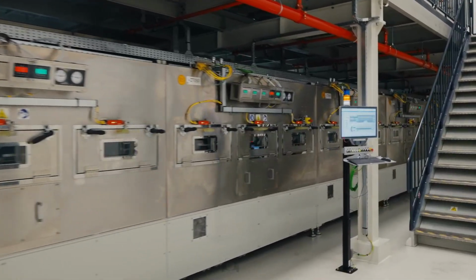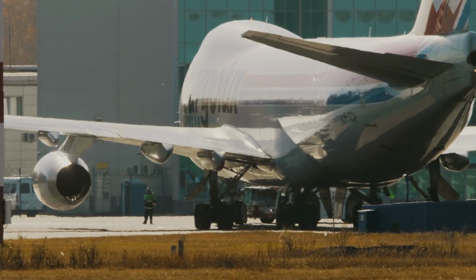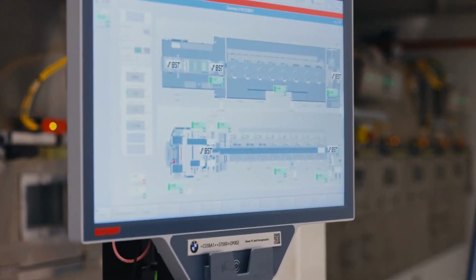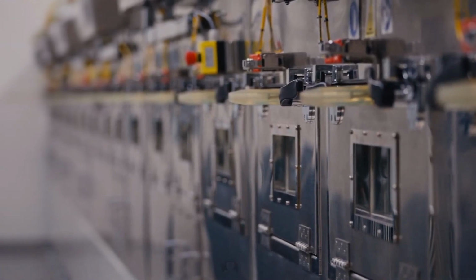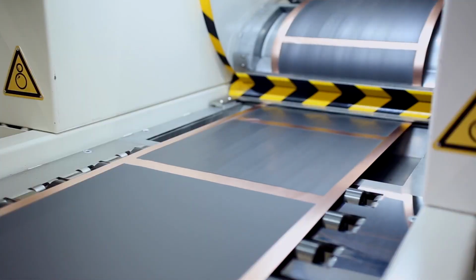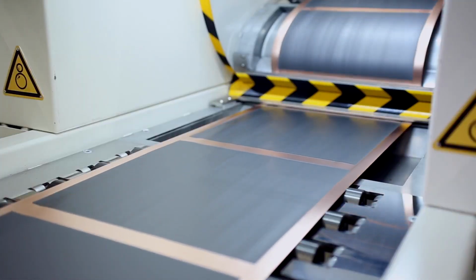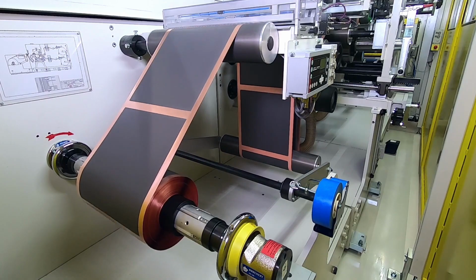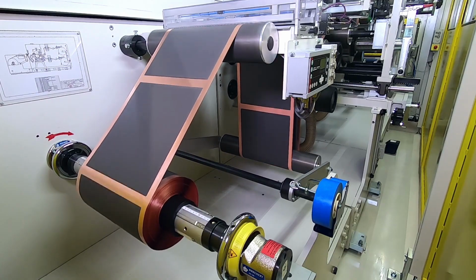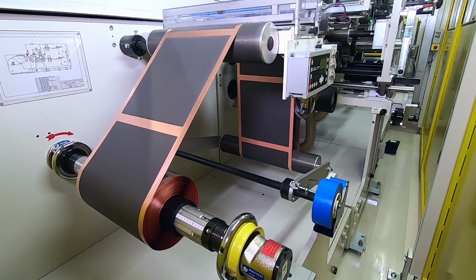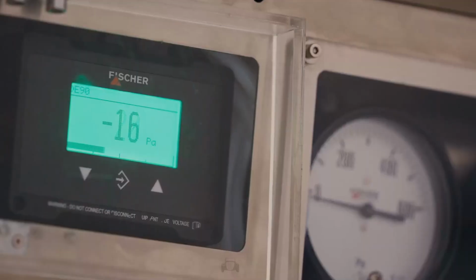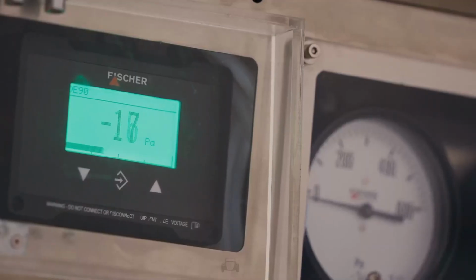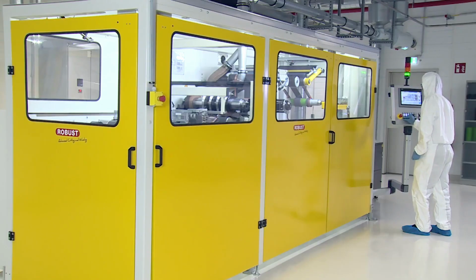After coating, the sheets pass through an 80-meter-long oven that's longer than a Boeing 747 to evaporate the solvent. Too much heat? The coating cracks. Too little? It stays sticky. The coated sheets are squeezed between two giant rollers to compress the slurry into a smooth, even layer. This step ensures the battery can store maximum energy without bulges or thin spots. Too much pressure can crush the material. Too little can leave air gaps.